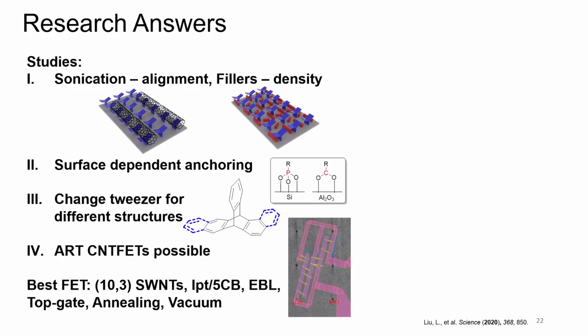Adding molecules to fill in the gaps promoted pi-pi stacking that increased the density, but actually affected alignment a little bit. I did also observe what is known as surface-dependent anchoring. Depending on the anchoring group used, it didn't work on other surfaces. So we needed to tailor the anchoring component to the type of surface that we were targeting for the system. Other nanostructures did not work. So the molecule itself will have to be tailored and changed for different systems.